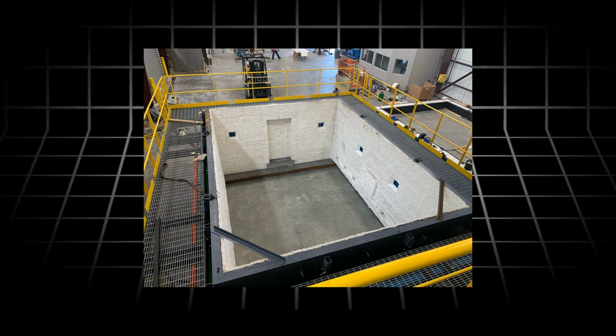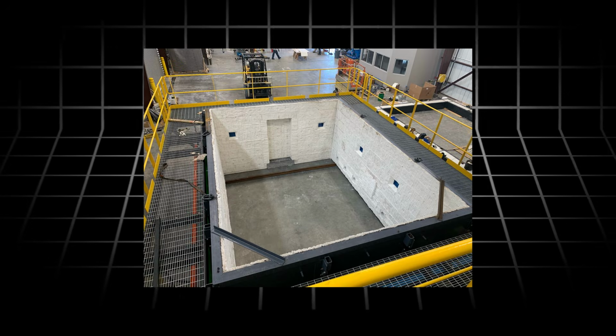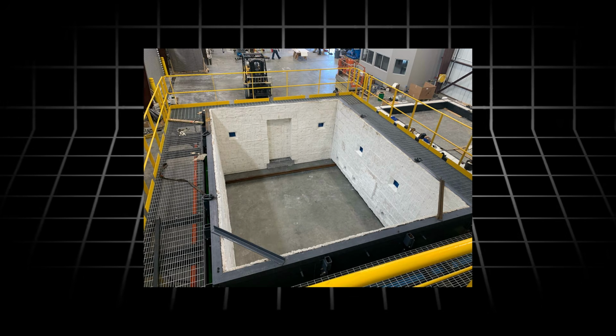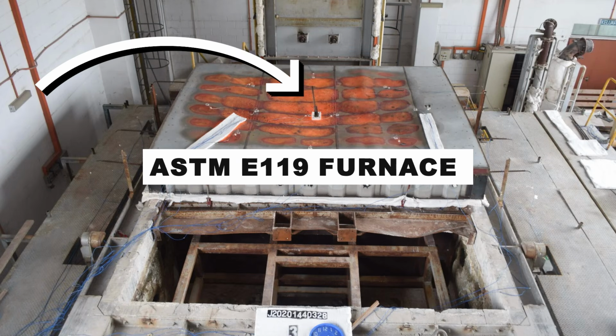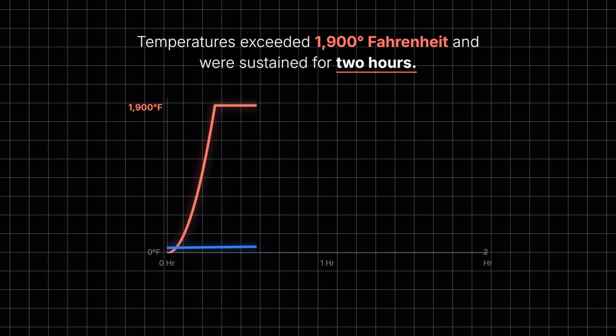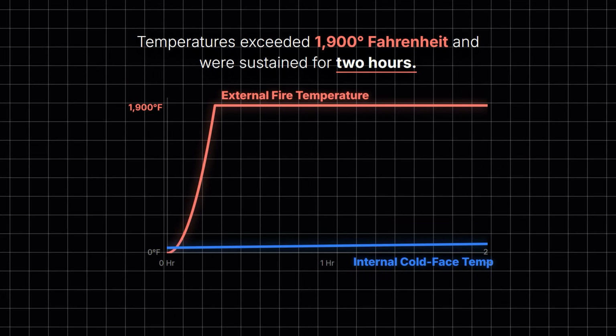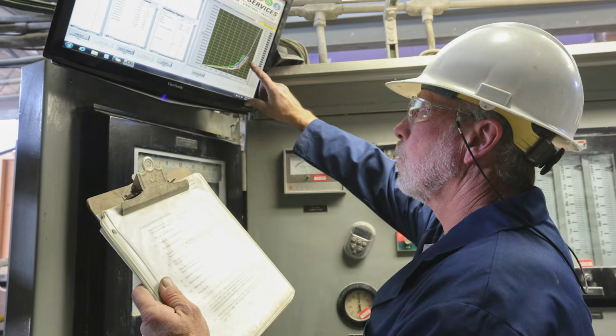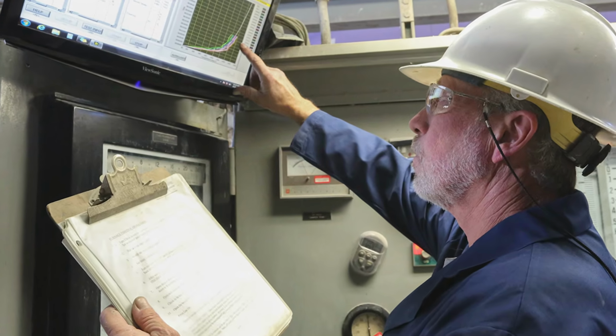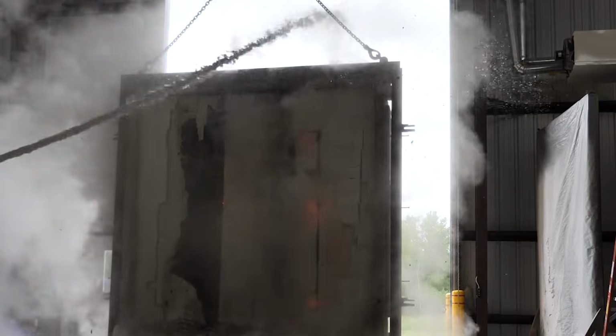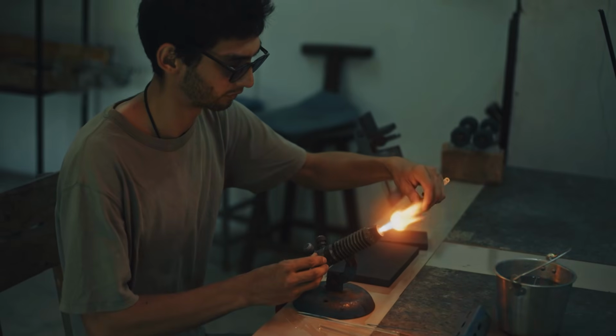On February 17, 2022, at Intertek Laboratory in San Antonio, Texas, a wall assembly built with double-layer 12mm MgO board on both faces of a steel frame entered an ASTM E119 furnace, the federal standard for structural fire resistance. Temperatures exceeded 1,900 degrees Fahrenheit and were sustained for 2 hours. During the test, magnesium hydroxide within the panels decomposed, releasing approximately 30 pounds of water vapor. The material was not merely resisting heat, it was actively suppressing it.